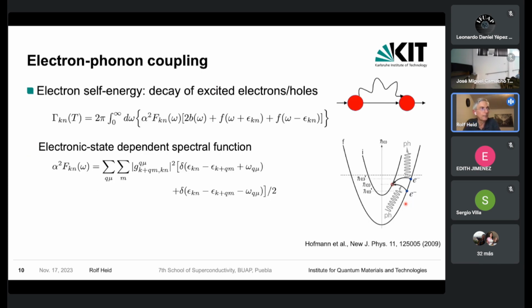Another quantity where the electron-phonon coupling enters and which plays a little bit of a role in my talk is also the electron self-energy as obtained by exchange of a virtual phonon. And don't bother about the formulas here, but essentially one can evaluate this diagram and obtain an expression for the line widths of the electronic state in such a form where here also a kind of state-dependent spectral function enters, which is essentially given again by an average over certain electron-phonon coupling matrix elements. And this expression essentially describes the virtual process. If you, for example, create a hole in an electronic band, and by virtual hopping of electrons from other bands or other places by simultaneous exchange, emission or absorption of phonons, that leads to a kind of finite lifetime or inverse line width of this electronic state, which can be expressed in this form.